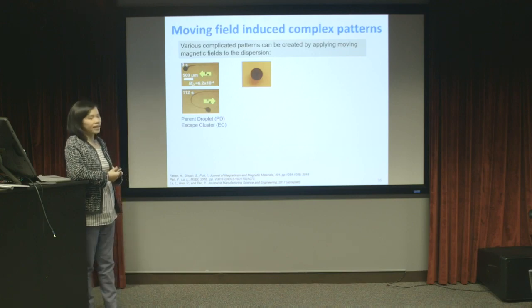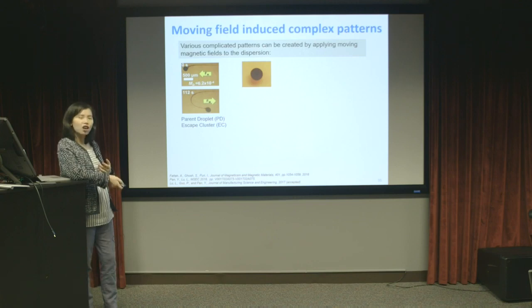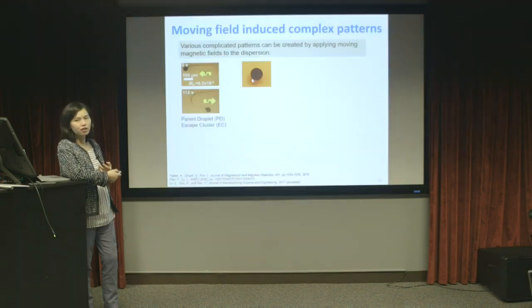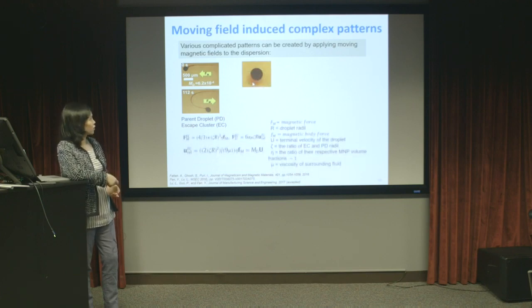And not just with a static magnetic field, we can use a moving magnetic field to attract a droplet of magnetic particles. So in this photo, the yellow region is liquid resin, and the dark droplet is MR fluid, magnetorheological fluid. It contains micron-sized magnetic particles, and we can model the magnetic force applied on the MR fluid droplet.